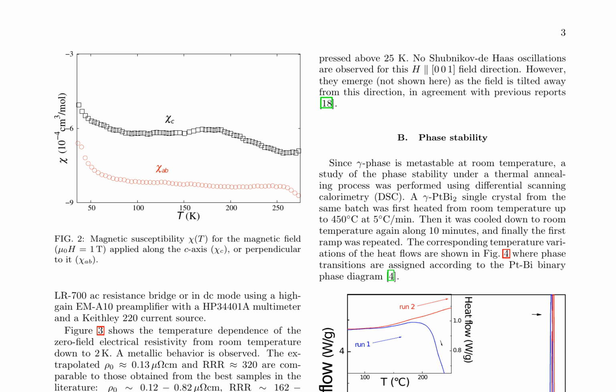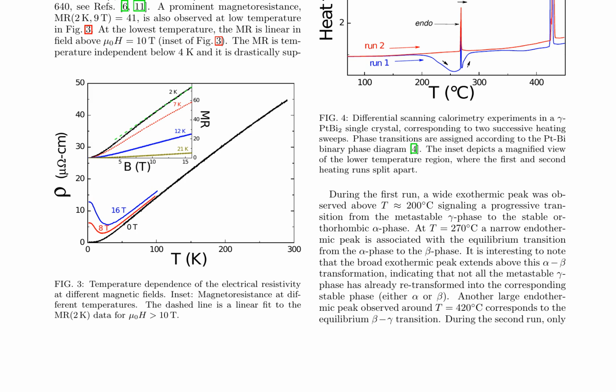A prominent magnetoresistance, MR(2 K, 9 T) equals 41, is observed at low temperature, which is linear in field above μ0H equals 10 T. The magnetoresistance is temperature independent below 4 K and is drastically suppressed above 25 K. No Shubnikov-de Haas oscillations are observed for the H parallel to [001] field direction, but they emerge as the field is tilted away from this direction, in agreement with previous reports.